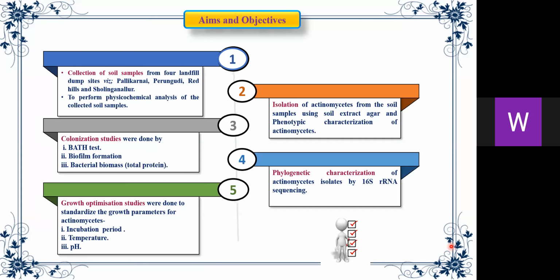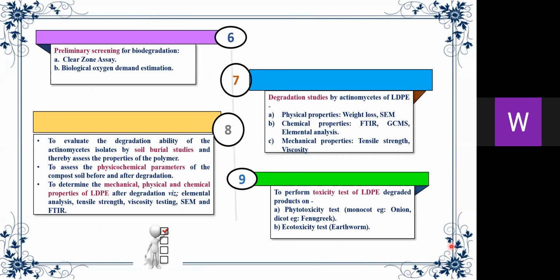The growth optimization studies were done to standardize the growth parameters like incubation period, temperature, and pH. Preliminary screening for biodegradation was done by clear zone assay and BOD. Degradation studies of LDPE by actinomycetes were done by physical properties through weight loss and SEM, chemical properties by FTIR and GCMS as an elemental analysis, and mechanical properties like tensile strength and viscosity, and to evaluate the degradation ability of the actinomycetes by soil